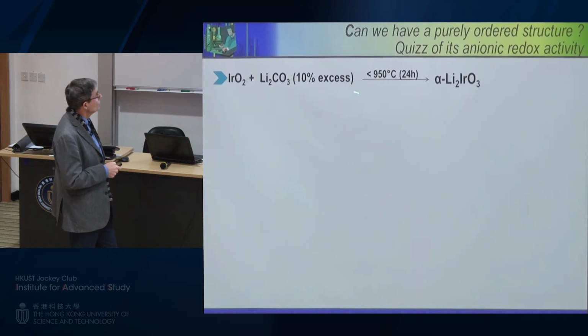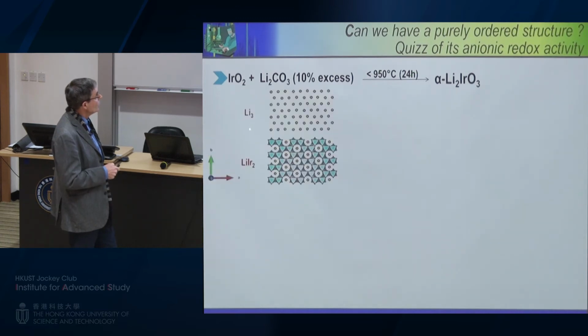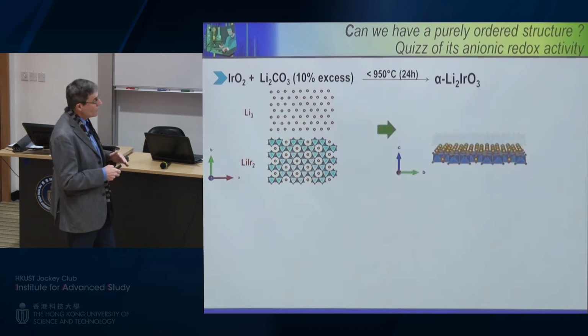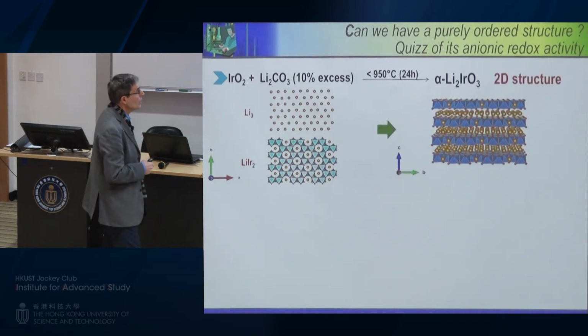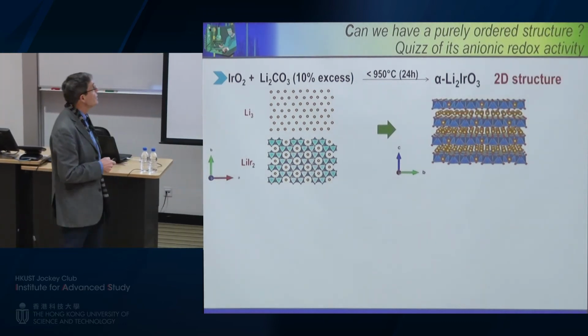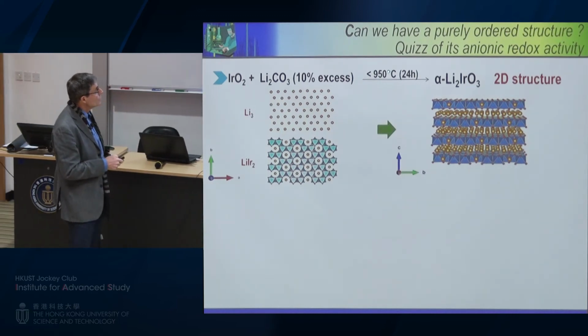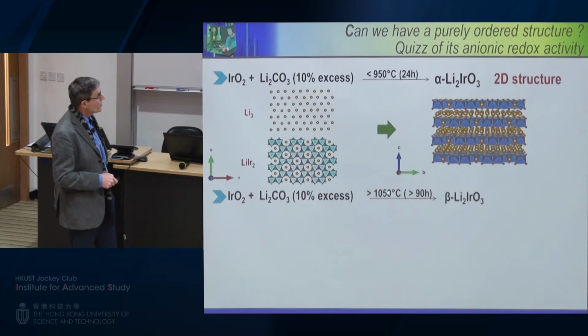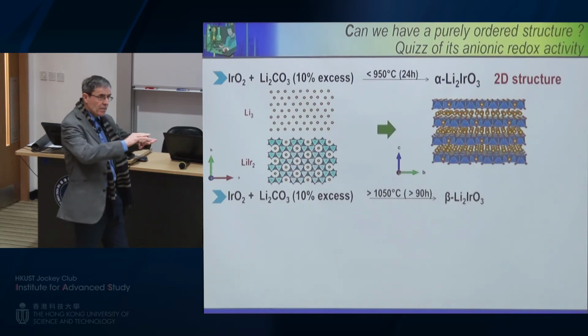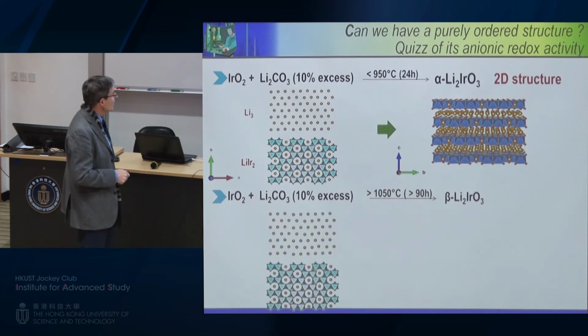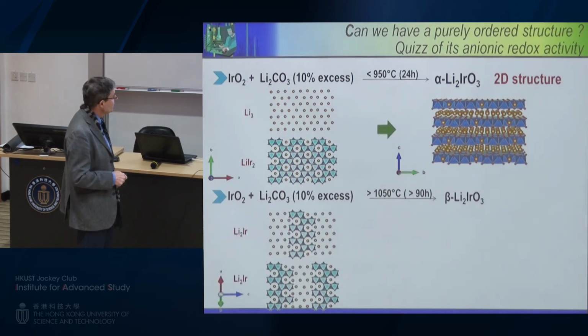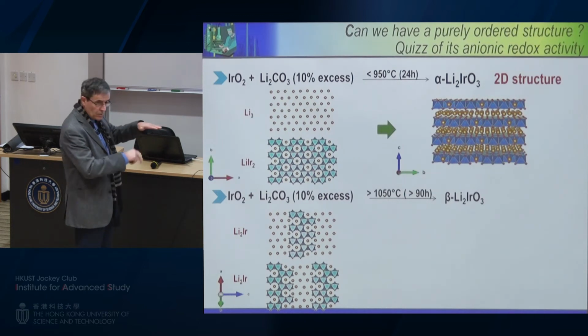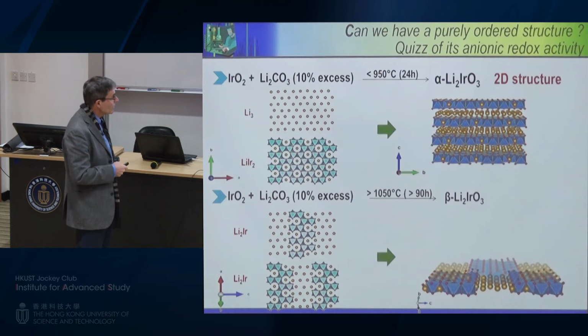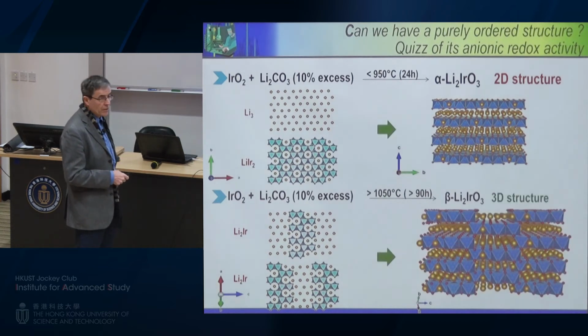This is a phase that I already mentioned to you, remember? This lithium-2 IrO3 phase that you prepare nearly under these conditions. And here you have these lithium layers and these metal layers, and when you do synthesis, what is happening? You are packing the layers on top of each other to get the 2D structure. And what we found is by simply changing the temperature, going to slightly higher temperature, 100 degrees C higher, you are going to see that we have a totally different stacking. Indeed, in this case, we are really mixing these different types of layers and finally packing two identical layers. And when we do so, as you can see here, look, now we are creating a 3D structure.